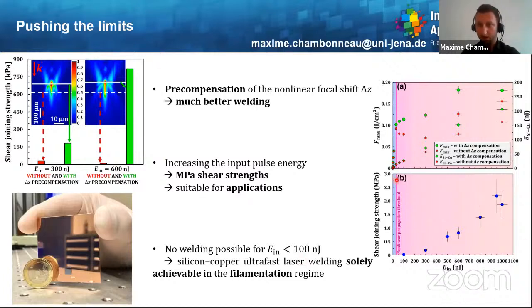Well, the results are essentially shown here on the right with those blue points, and one can see that it is possible to reach megapascal, like more than 2 megapascal shear joining strength with this strategy for around 1 microjoule input pulse energy. And this value of more than 2 megapascal is suitable for applications.